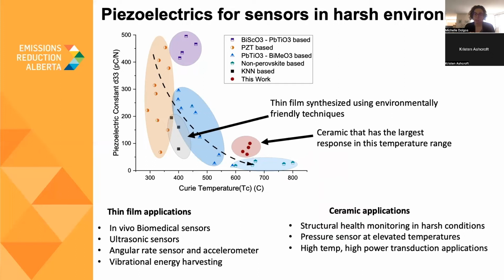So we've worked in two spaces here. So we're looking at thin films, and we've been able to synthesize a thin film material that we've developed this environmentally friendly synthesis technique using aqueous solution. And that the precursor solution, as well as the synthesis technique, we're in the process of the full patent application for that right now. That particular material does not have any lead in it, and it also works at a higher temperature than the industry standard.